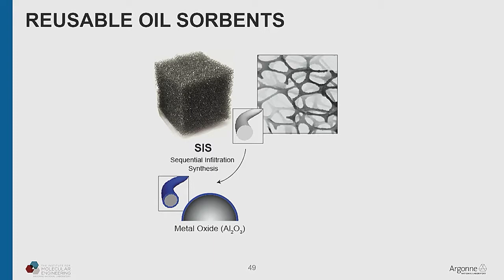And that is not because aluminum oxide or zinc oxide have the properties we want. What it does is it provides powerful attachment points for the next step, which is a silanization reaction, where we can attach silane molecules to the surface very robustly, which have tail ends having the property that we want, in this case, oleophilic. One can imagine attaching different molecules for a different purpose, and that's one of the things we're playing with now. Now, no one had ever done SIS on a three-dimensional thing like this before.